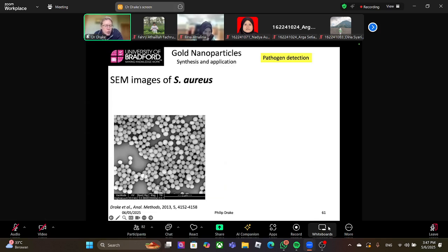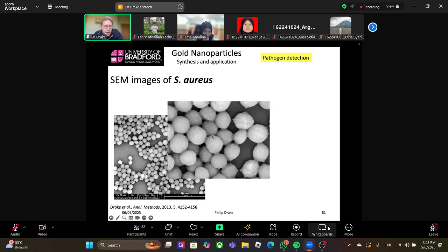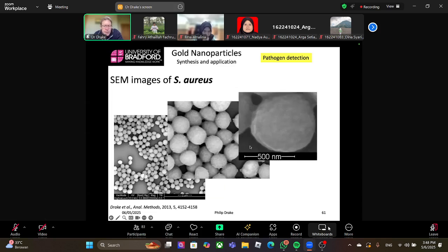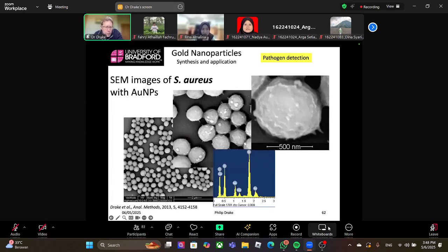This is an SEM of Staphylococcus aureus. This is the bacteria, the round bacteria. That's the surface zoomed in. If we mix it with the gold particles, we can see the gold particles on the surface. So these bright spots are the gold nanoparticles bound to S. aureus. So that's one of the nanoparticles on the surface there. We can also confirm that by EDX characterization. We get a little gold peak saying gold metal is there.